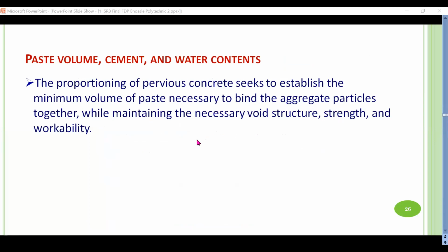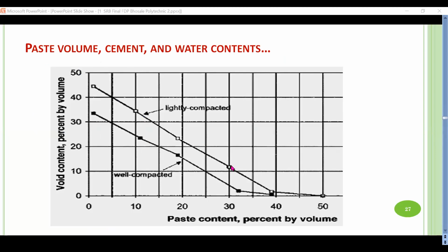Another parameter that affects the performance of pervious concrete is the paste volume. How much paste volume is there? What is the quantity of cement, and what is the water content added while making the pervious concrete? This graph shows the void content against the paste content percent by volume. If the paste content increases, as you can see on the x-axis, the void content decreases, and hence the permeability of pervious concrete decreases. If some 20 or 25% voids are expected, then the paste content should not be greater than 12 or 15%. Such information will be useful in designing pervious concrete.